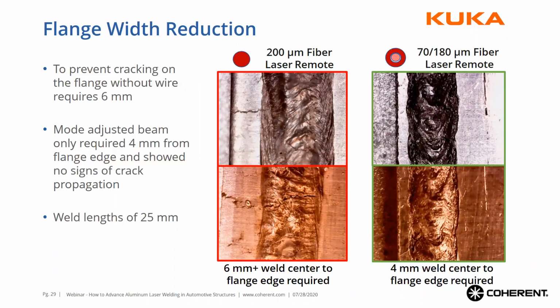This also shows a similar study that we did, where they were doing a flange reduction study. The left image shows a standard fiber laser with the weld 6 millimeters away from the edge of the flange. See that again, the heat builds up at the end of the flange, and you see micro cracks and cracks all over the place. On the right side, they did the study 4 millimeters away from the edge of the flange, from the center of the weld to the edge of the flange, and you see no cracking again. So they confirmed the same results that we had in our lab.